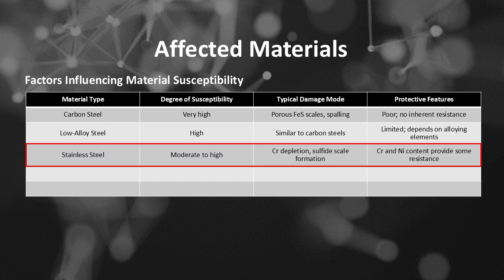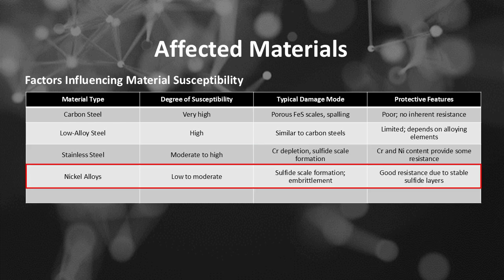If material type is stainless steel, then its degree of susceptibility is moderate to high, then its typical damage mode is Cr depletion, sulfide scale formation, then its protective features is Cr and Ni content provide some resistance. If material type is nickel alloys, then its degree of susceptibility is low to moderate, then its typical damage mode is sulfide scale formation, embrittlement, then its protective features is good resistance due to stable sulfide layers.